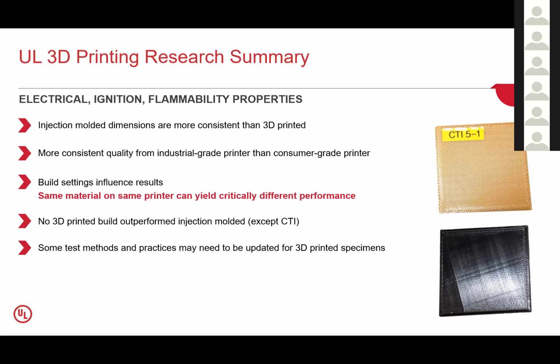If you don't take anything else away, this is probably the most critical one, is that the build settings do influence the results. That same material on the same printer can yield critically different performance. We saw that with the flammability. We saw it with the comparative tracking index. We saw it with volume resistivity. We saw it with dielectric strength. We saw it with the hot wire ignition.